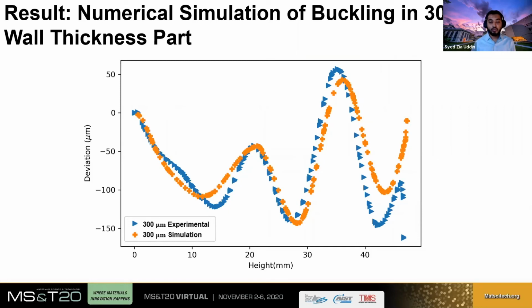and we are figuring out some of the hyperparameters for that simulation, so that we can model thicknesses below 300 micron. But starting at 300 micron wall thickness, it is very much possible to get very good correspondences between simulation and experimental results, as you can see. And these simulations can be very handy